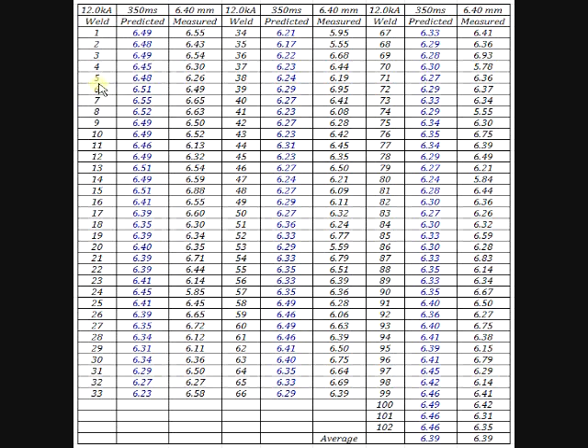This is from number 1 to number 33. Okay, and number 34 to number 66 is listed here. The blue color one is the predicted nugget diameter, and the measured is over here. We did 102 welds because 100 just doesn't divide by 3. So we took all 102 welds and averaged them.